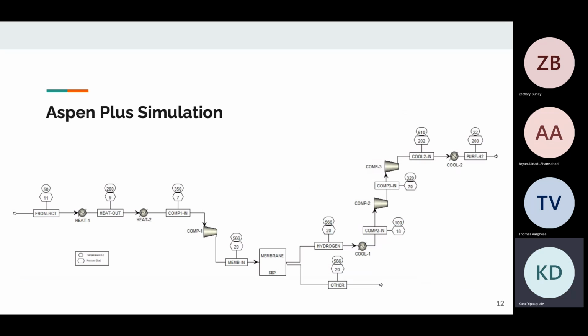We began the process from the heat exchanger outlet while disregarding the flash drum in the original design, as the water has already been purely separated and will be sent to the wastewater treatment plant. The inlet conditions are displayed at 11.5 bar and 50 degrees Celsius with a molar flow rate of 9,262 kmol per hour. The inlet includes 59% hydrogen, 21% carbon dioxide, 16% carbon monoxide, and negligible amounts of nitrogen and water.